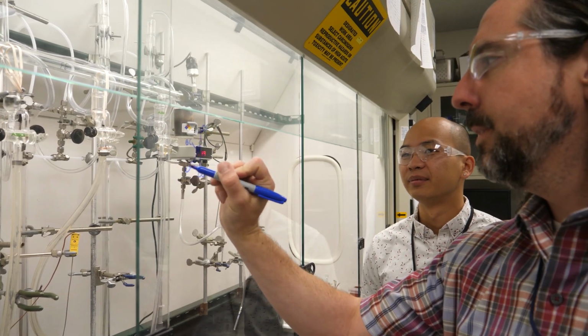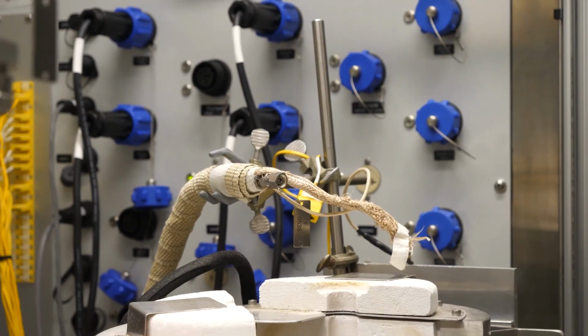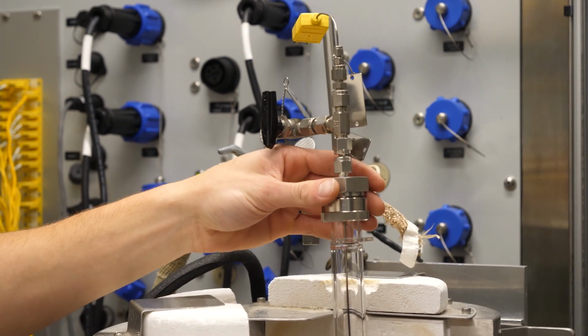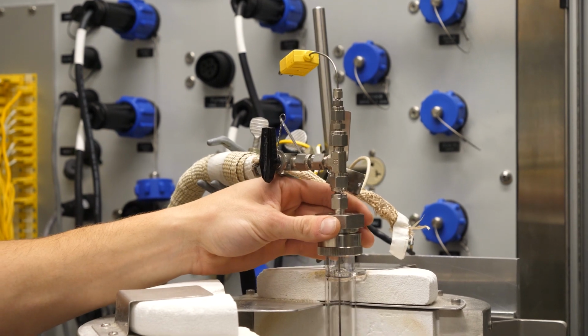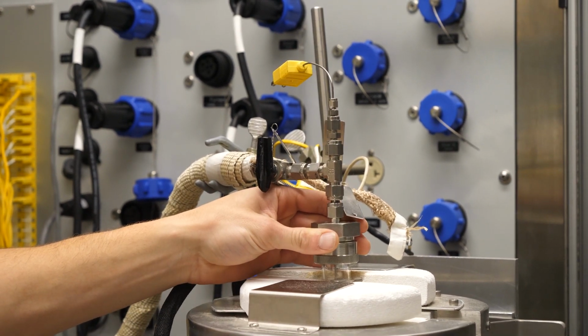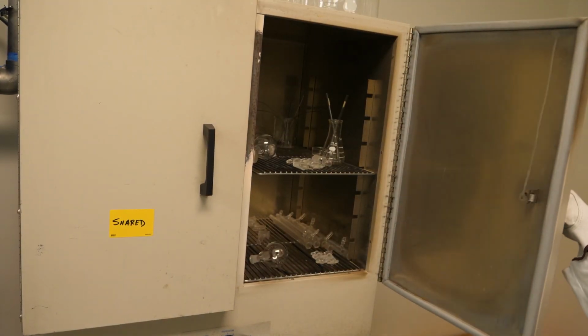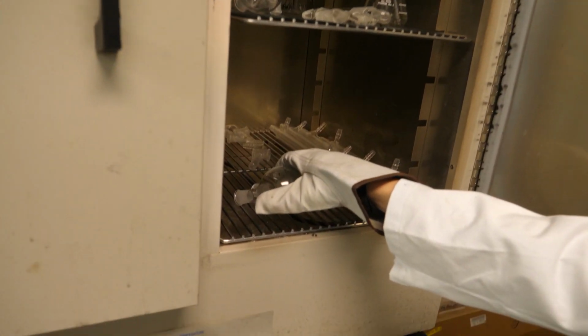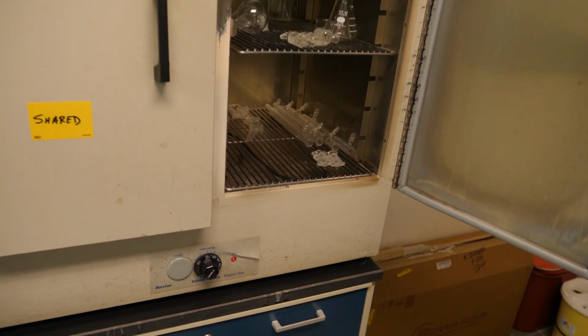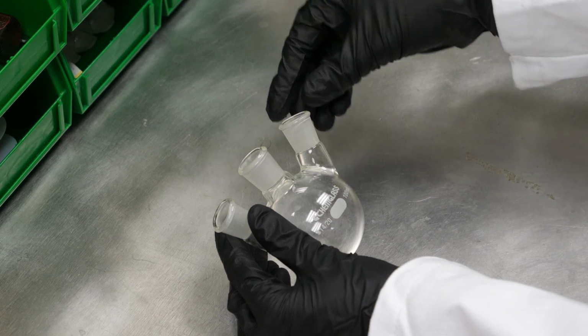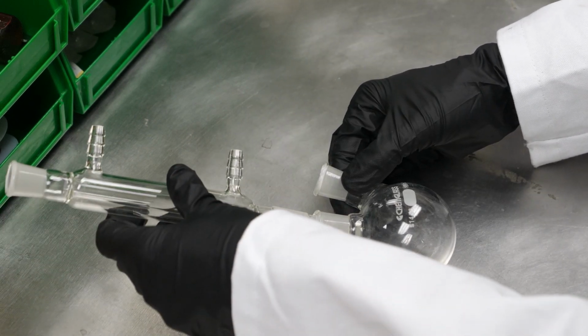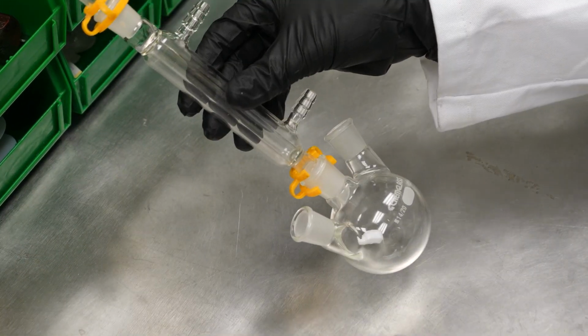within ChemCatBio. I'm Dan Ruddy, and I'm a senior scientist at NREL, specializing in the design and synthesis of catalyst materials. In addition to standard bulk synthetic routes, where the metal carbide is synthesized at very high temperatures, we're also interested in low-temperature solution synthetic routes to metal carbide nanoparticles. The high level of control afforded by the mild solution synthesis conditions enables us to create model catalyst systems with key features that have been predicted by our computational team.